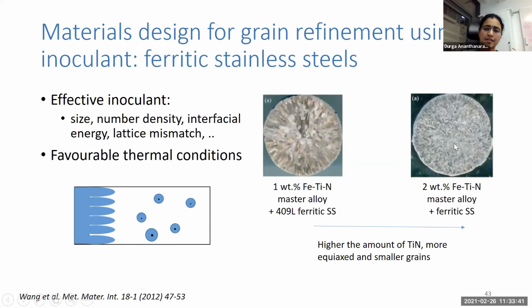So then in our project, we decided to apply this method of using inoculants to ferritic stainless steels. If we want to introduce an inoculant, there are several factors that we have to consider. One, it has to be in the right size range for it to be effective. Then it needs to be of a certain number density, the interfacial energy should be favorable, and the lattice mismatch, and so on. Plus, we also need to have favorable thermal conditions in our process for it to be effective.